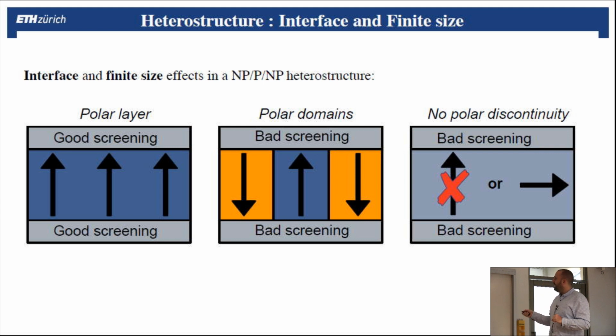Another possibility, instead of doing this, is to rotate the polarization from out of plane to in plane, because the material will be large in plane and thin out of plane. So that means that here it doesn't really matter if you have the charges accumulated, because they will be so far away that it's not a problem. And by doing so, you also remove the charges at the interface.